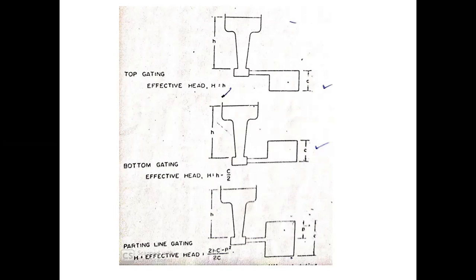The third one is half the casting in the drag box and half the casting in the cope box. The formula to calculate the effective pouring head is H equal to 2hC minus P squared upon 2C. You can see it in the sketch. This is most important. Normally, the third photograph covers most castings, at least 75 to 80% will have the casting in the third category. The first and second categories are 10% each, not more than that. But please note that calculation of effective pouring head is most important while calculating the choke area.